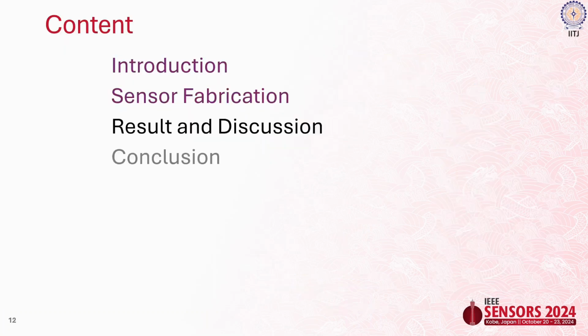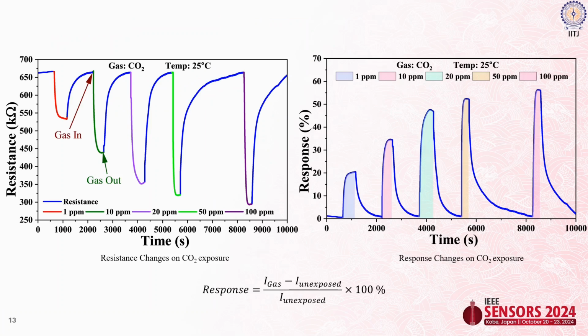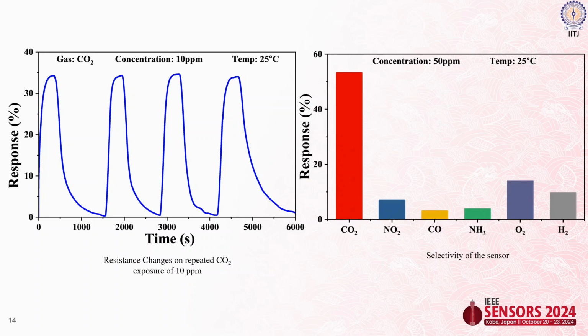Then we tested it for carbon dioxide, starting with 1 ppm, going up to 100 ppm. For different gas concentrations the response is changing, and we are getting an appreciable response even for 1 ppm, around 18% response for 1 ppm, going up to 56% for 100 ppm. We also checked the selectivity, and it has good selectivity towards CO2 compared to NO2, CO, ammonia, oxygen, and hydrogen. We also checked the repeatability, and the greatest advantage that we are getting here is that we are not applying any temperature. All this is at room temperature.